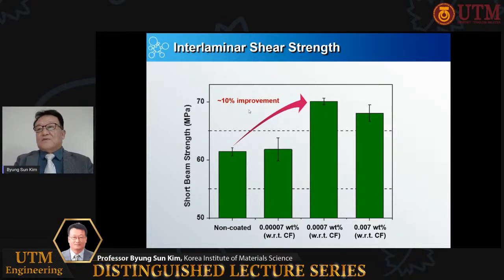The graph shows the effect of graphene oxide coating on the interlaminar shear strength. Interlaminar shear strength is an important material property for the design of laminated composite structures subjected to transverse load. Only with 7/10,000 of a weight % of graphene oxide coating, the interlaminar shear strength is increased by almost 10%. Previously, the same results were obtained with more than 1 weight % of carbon nanotubes.